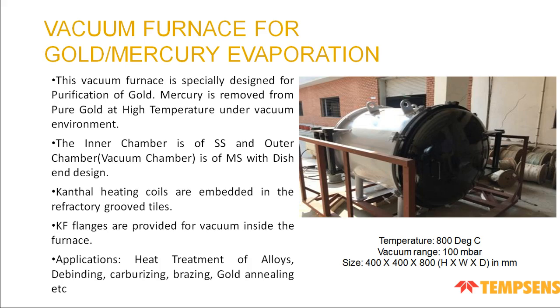So to get a pure form of gold, this furnace has been used, and this vacuum furnace is specially designed for purification of the gold, and mercury is removed from the gold at high temperature under vacuum atmosphere. So when the material is heated at 800 degrees centigrade, the mercury is evaporated in this furnace, and it gets collected in the bottom of the furnace.